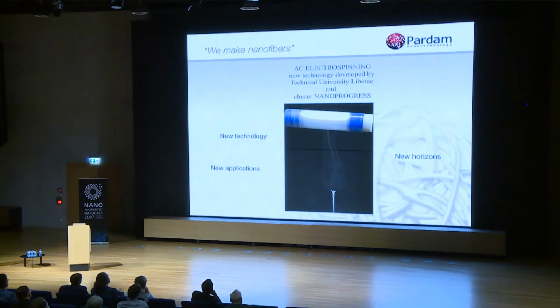And this is the picture of the new technology. We are part of the team developing this technology. We are getting back to electrospinning. The electrospinning I was speaking about at the beginning of my presentation is based on DC. So basically you need 2 electrodes to drive the fibers from the polymer solution. AC electrospinning was developed and patented by Technical University Liberec, which is our partner in the Czech Republic, and Cluster Nanoprogress. And it's based on AC, so you don't need the opposite electrode to create the fiber forming process.